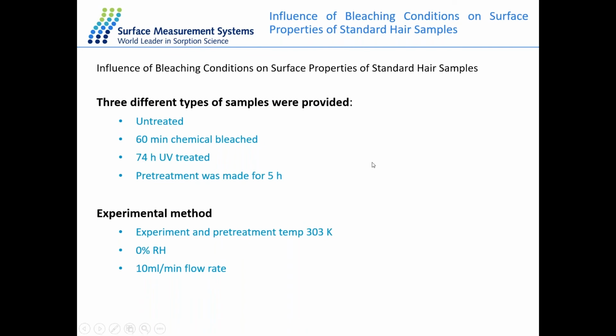The next example here is looking at the influence of bleaching conditions on some hair samples. In this case, the different hair samples that we're looking at are untreated, chemically bleached samples, and UV treated samples. And we've preconditioned the samples for 5 hours. The experimental temperature was 303 Kelvin. We didn't apply any relative humidity, and we had a stable flow rate of 10 ml per minute.